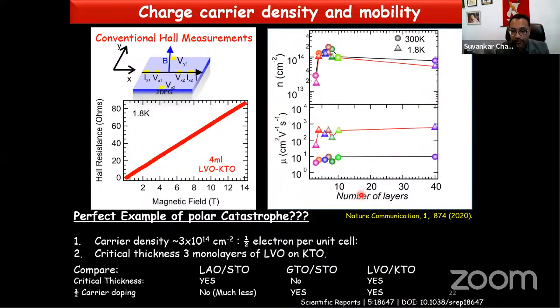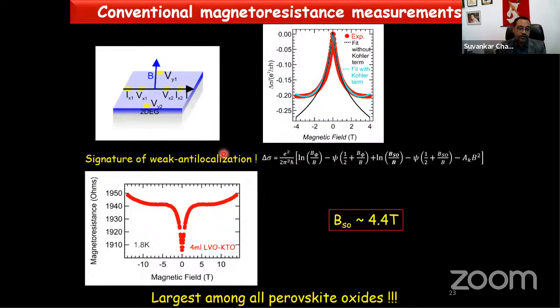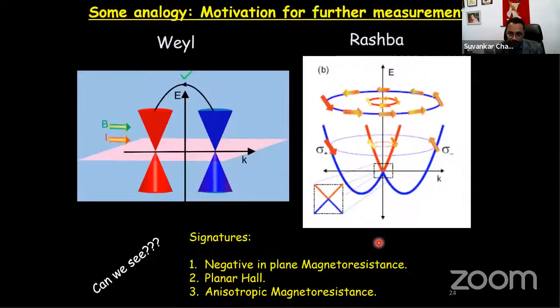And so this is the number of monolayers grown, and this is the mobility versus charge carrier density, versus the number of monolayers of the lanthanum vanadate thin film grown. Then we performed the normal magnetotransport measurement where you send the current along the X direction, apply the magnetic field along the Z direction, and measure the voltage along the Y direction. And you can see the appearance of weak antilocalization, which is a signature of strong spin-orbit coupling. Fitting this equation, we could figure out the amount of spin-orbit coupling is around 4.4 Tesla, which is the largest among all perovskite oxides.